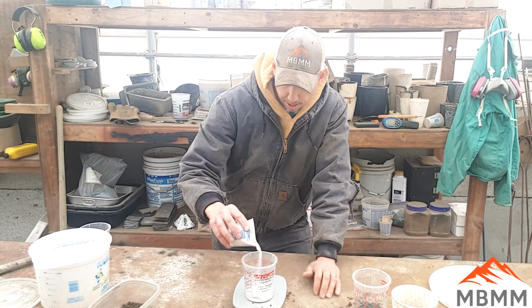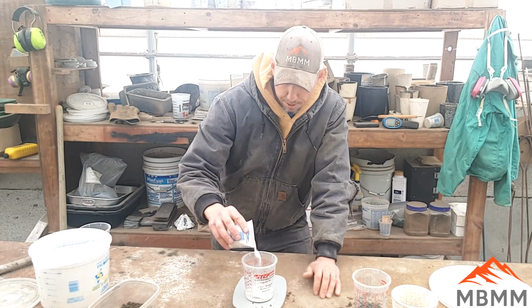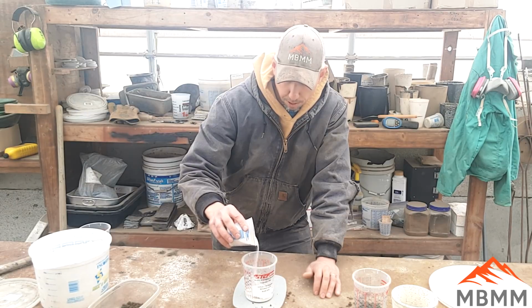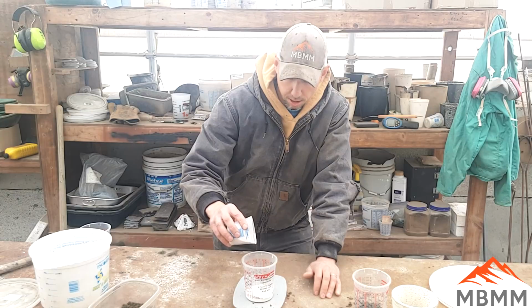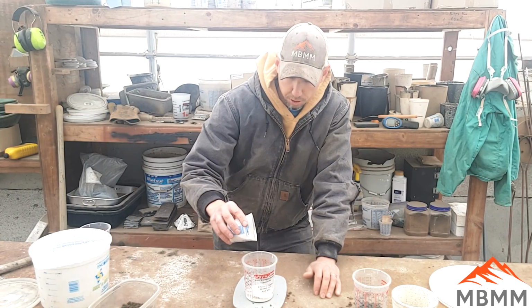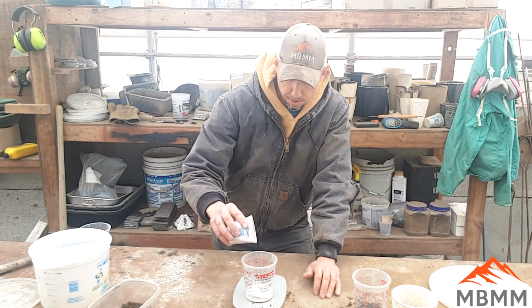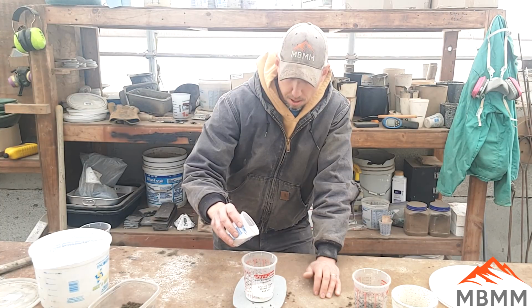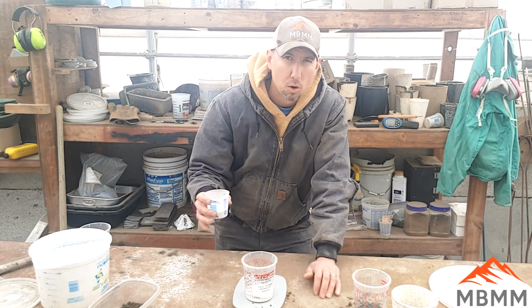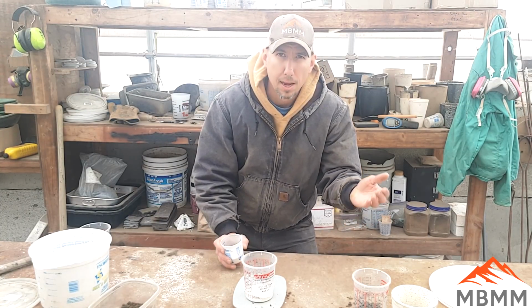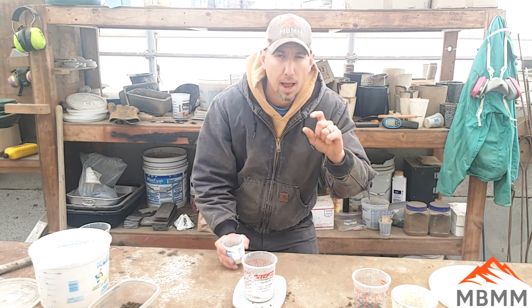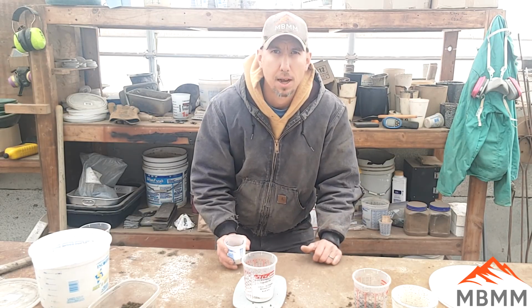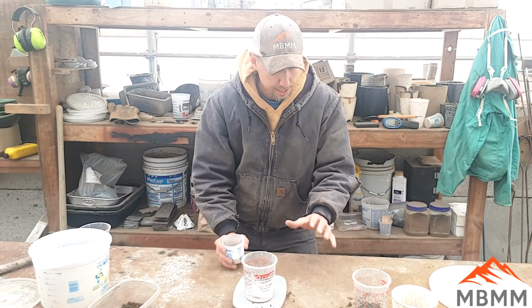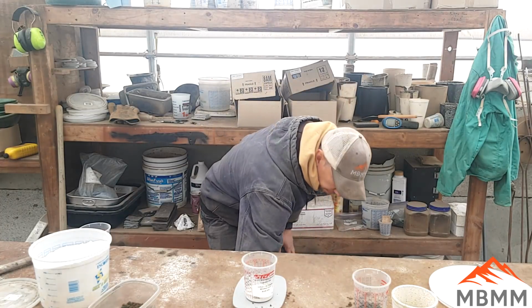And the silica protects the fire clay crucible, I found. I found if you don't use any silica, your crucibles get eaten up really fast. But if you add too much silica and/or too much borax, the slag becomes so acidic that you have a matte layer, and it's not basic enough to absorb the matte. So again, this is what I found works really well for me.